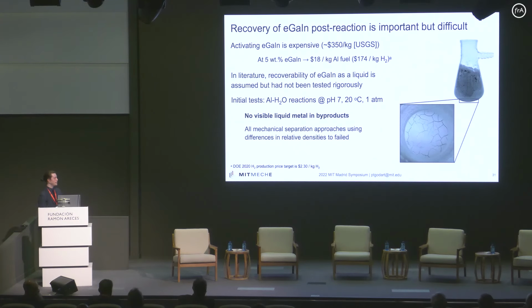The DOE hydrogen target is about $2.30. You can do it with methane reforming for about $1 per kilogram of hydrogen. So this is just simply not sustainable. Not only that, we're just dumping gallium and indium down the drain, which is also not good. And again, as I mentioned previously, no one knew how to do this recovery.